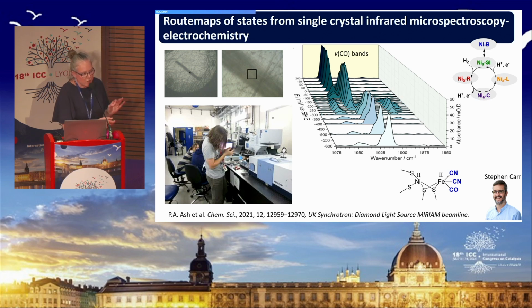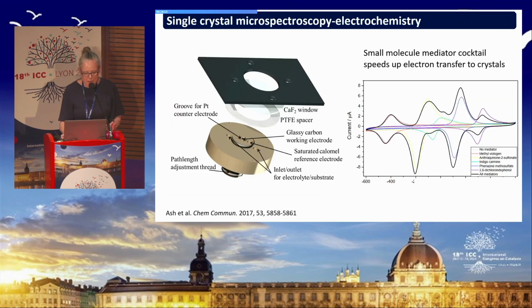So if you just add a reductant or add hydrogen, you're likely to hit some potential where you've got a real mixture of states, whereas with the electrode potential we can dial up very specific states. Now I'll just step back for a moment to show how that works. We've built this cell in-house, and we have a mirror-polished carbon electrode, and the crystal sits on that electrode, and as we apply a potential at the electrode, the crystal then responds to that.